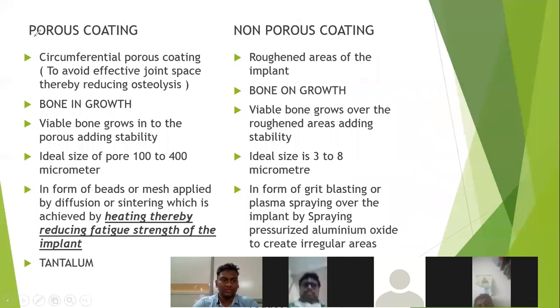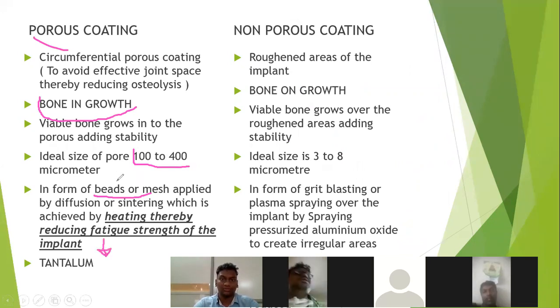So porous coating is done in the form of beads and meshes. There will be minute pores present over the femoral component, at a size of 100 to 400 micrometers. It works on the principle of bony ingrowth. This is what happens in the porous coating. But the disadvantage of porous coating is that we need heating, and this reduces the fatigue strength of the implant. So we usually do not prefer the porous coating.